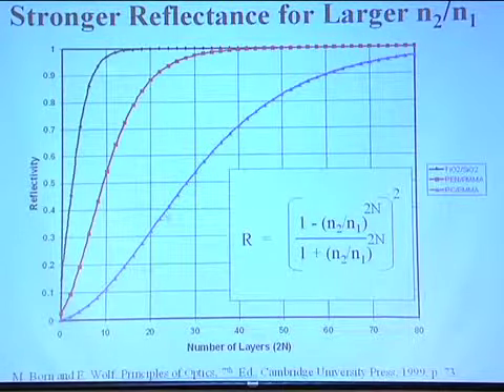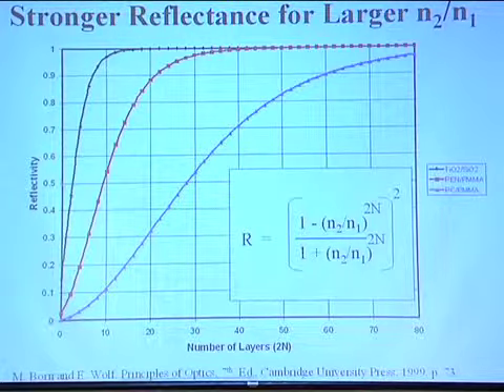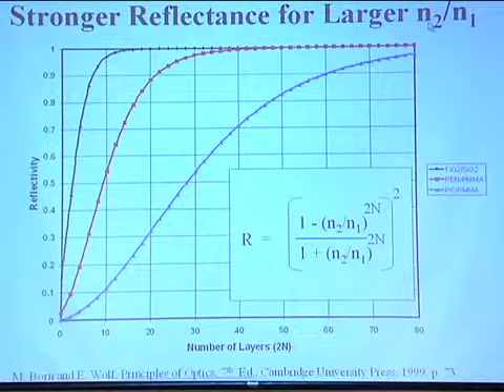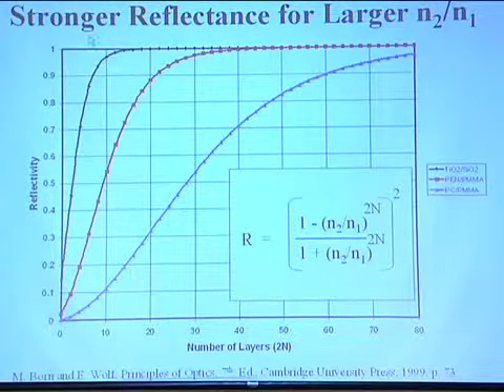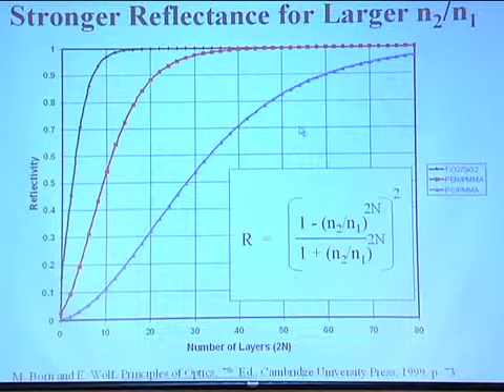And this shows the power of reflectivity with the difference in refractive index. So the difference between the refractive index of material 1 and the refractive index of material 2 allows you to get materials that are incredibly reflective. We've made films that are 99% reflective. They're the most reflective mirrors in the world. Your typical silver-coated glass mirror in your bathroom is 94% reflective, and an aluminum mirror is typically about 90% reflective.